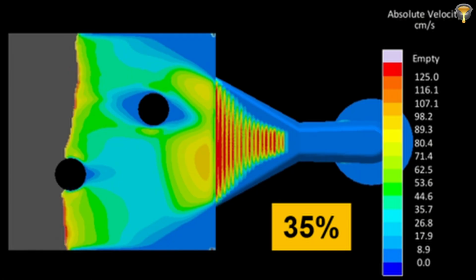It starts when you get to a higher solid fraction, something around 35% and above, where you have so much solid fraction that you can fill a tool in a laminar way, and it doesn't give you that turbulent fill. It really goes through laminarly. But with 35% solid fraction and above, you also have to modify the tools, because if you have a normal gate, you just squeeze out that slurry, the liquid goes in, the solid stays behind the gate, and then you have a terrible casting throughout. And that is why most trial castings really fail. Because of the gating. Yeah, the gating and everything.